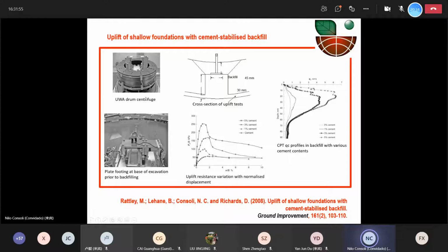And so we have tested, and we proved that instead, we can see in this figure here, normalized, this is like the pull-out force that we have here would be about 50. And then if we put 1% of cement in this material that's backfill, we can even double the maximum load. If we put 3% of cement, we can increase to 170, let's say, the load that's normalized here, so the applied pressure, a stress in the end here.